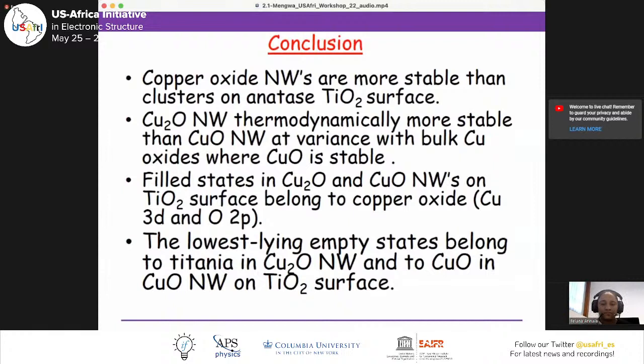Now we also see filled states in Cu2O and CuO nanowires belonging to the copper oxides. The lowest lying empty states belong to TiO2 in the Cu2O nanowire structure that's coupled with TiO2, and to CuO in the structure that's coupled with the TiO2.